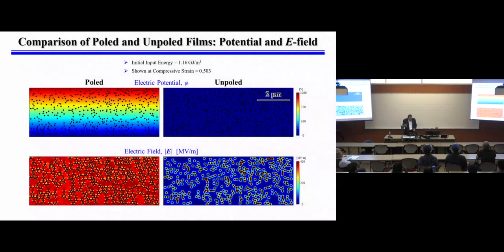It has piezoelectricity and flexoelectricity. The difference between the poled and unpolled material is that the piezoelectricity gives you an overall potential difference, voltage difference, between the top and bottom surface. The unpolled material practically has no macroscopic voltage difference or potential difference. But again, it's the local areas with the highest E field that dominate. So flexoelectricity dominates the local high E field areas around the particles, such that even though the E field distributions look quite different for these two materials, their overall behavior is not extremely different. They're only 20% different, as I will show.